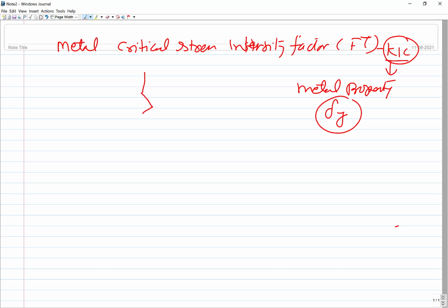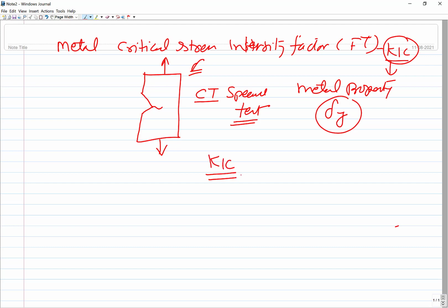What it shows is this: there is a crack in a metal, so we apply a tensile load and try to see at what stress level, under what loading conditions, this crack starts to grow. That resistance to crack growth is quantified in terms of the stress to be applied using the external tensile loading system. This is a typical compact tension, CT, specimen test for quantifying K1C. Let us not get into the many details. The K1C is a metal property, a critical stress intensity factor used for design purposes.